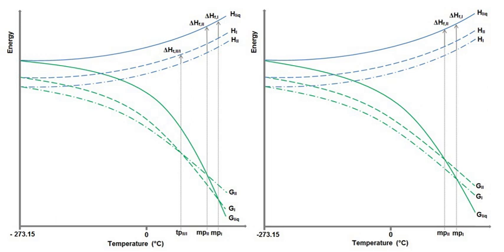In 2006, a new crystal form of malic acid was discovered 124 years after the first crystal form was studied. Malic acid is a chemical manufactured on a very large scale in the chemical industry and is a salt-forming component in medicine. The new crystal type is produced when a co-crystal of caffeine and malic acid 2:1 is dissolved in chloroform and when the solvent is allowed to evaporate slowly.